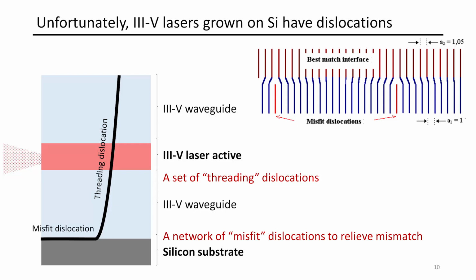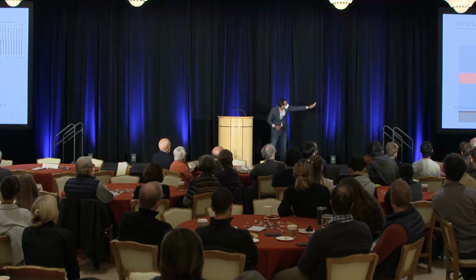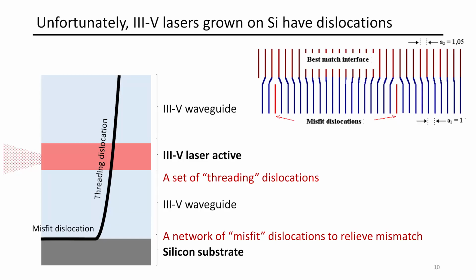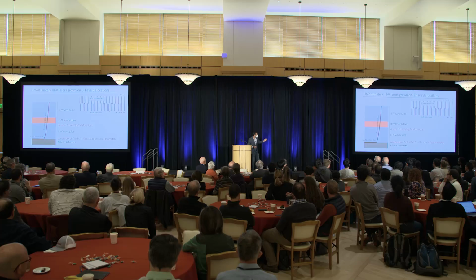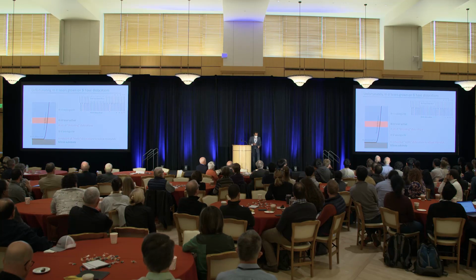But a dislocation is like inserting a sheet of paper in a stack of paper, right? So when you insert a sheet of paper, you have the paper's edge, but then you also have the other two edges on the side, and those actually are what we call the threading dislocations. So these are the dislocations that extend from the misfit dislocations at the interface, but all dislocations need to terminate on a free surface. This is one of those weird rules of dislocations. And so we get these things that go up through our device. Very, very sad, very horrible.